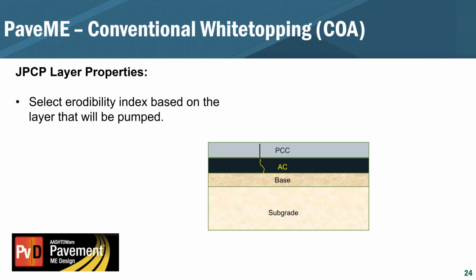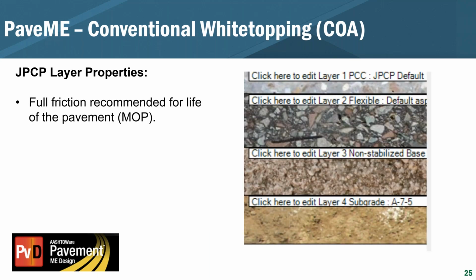So a lot of times the material you're eroding is that base layer. And if you look at some of the LTPP data, it supports this, where we have different concrete pavements on asphalt stabilized bases, and the erodibility of the layer below the asphalt layer does play a critical role in the development of faulting. So I think that's one important thing to see.